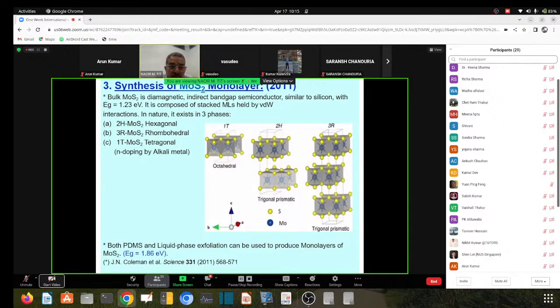The bulk of MoS2, which is the first one, is a very popular transition metal dichalcogenide. This is the original one. It is diamagnetic, and it is a semiconductor with an indirect band gap when it is in the bulk structure, similar to silicon. The energy gap is 1.23, whereas silicon is 1.14 or something. It is composed of stacked monolayers held by van der Waals interactions. In nature, it exists in 3 phases. It exists in 2H, the hexagonal MoS2. These structures are on the right side.